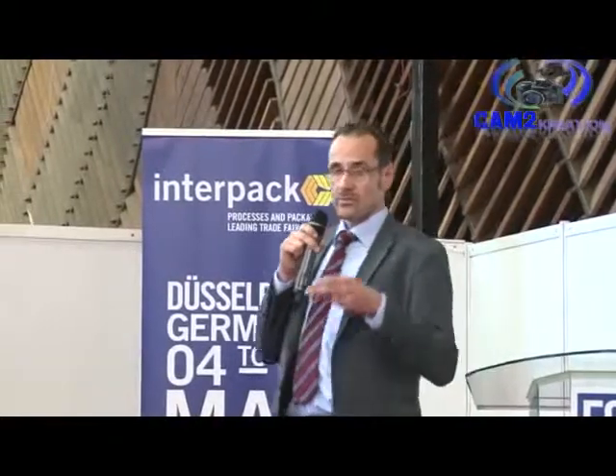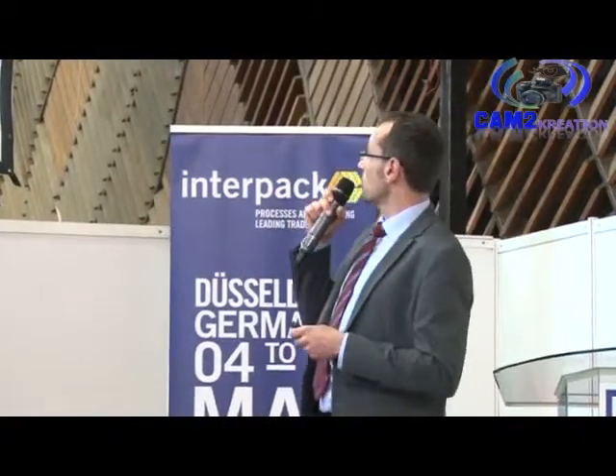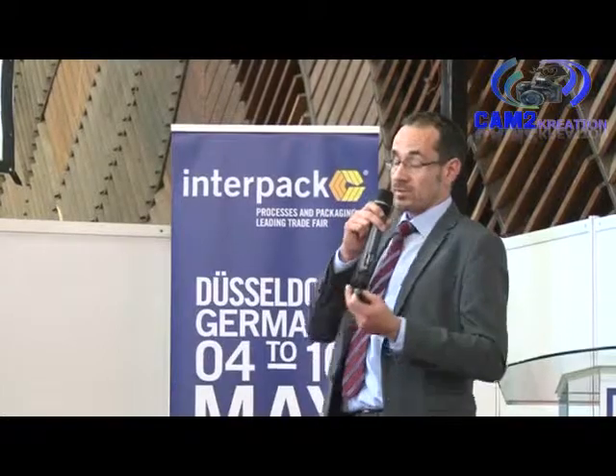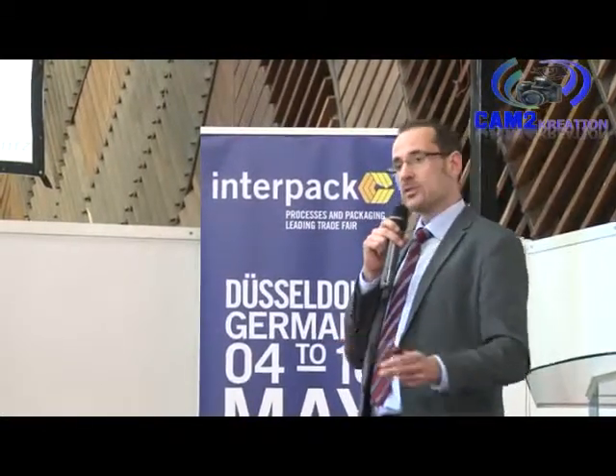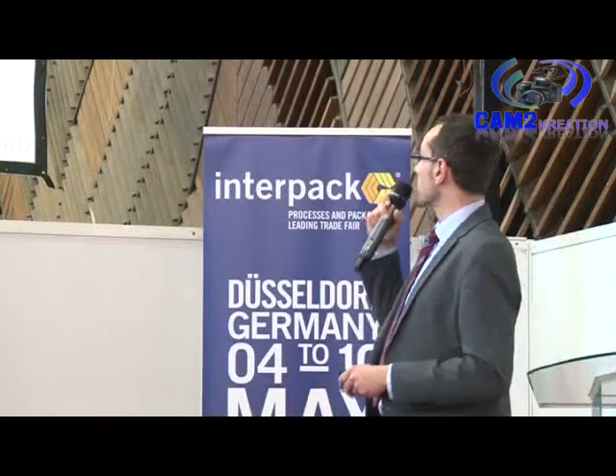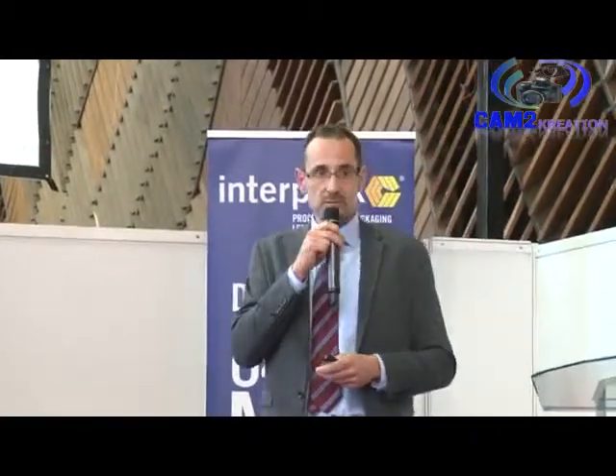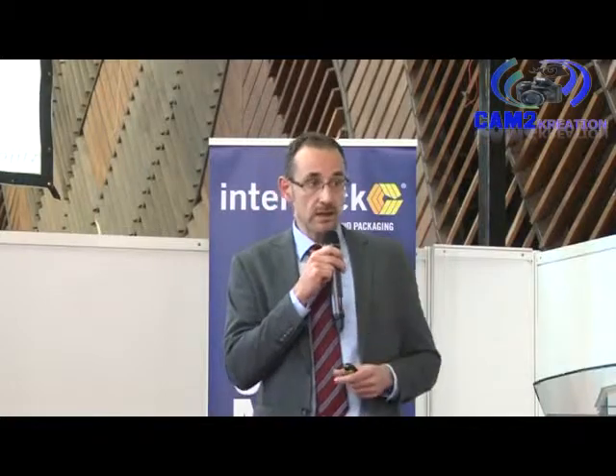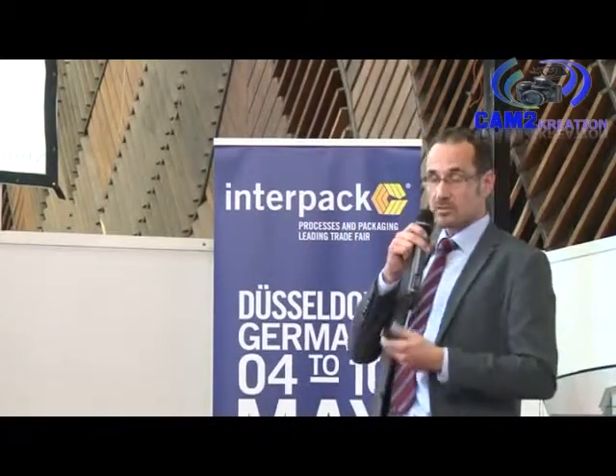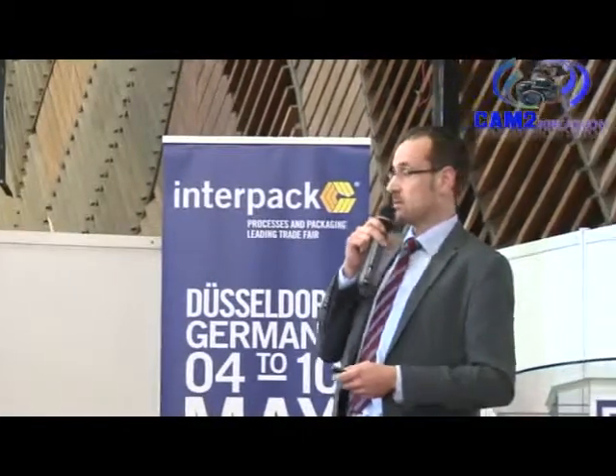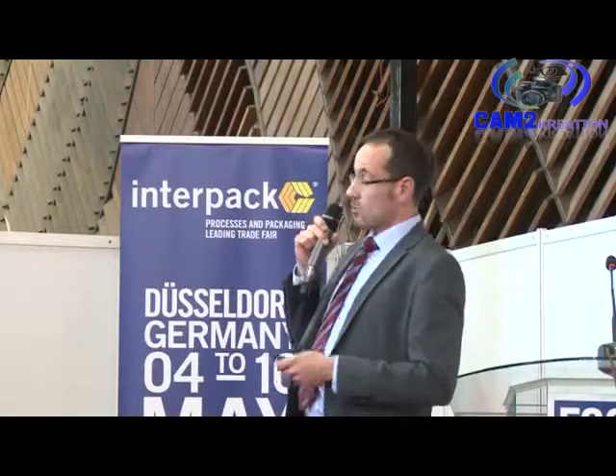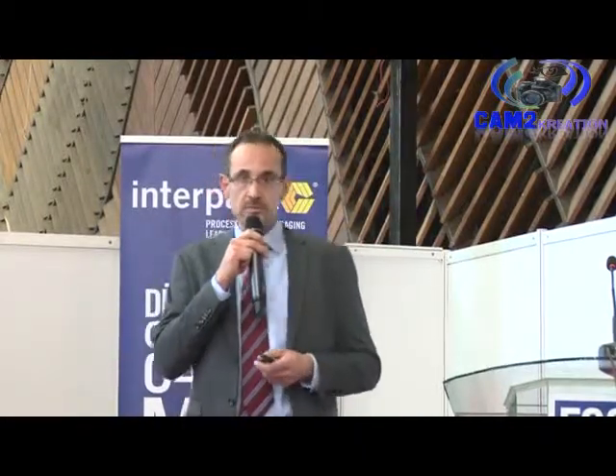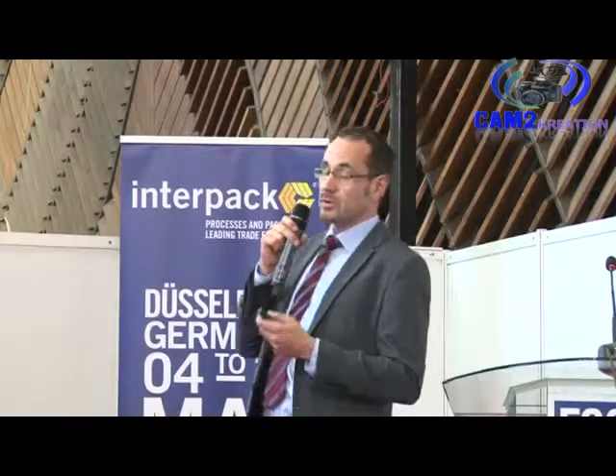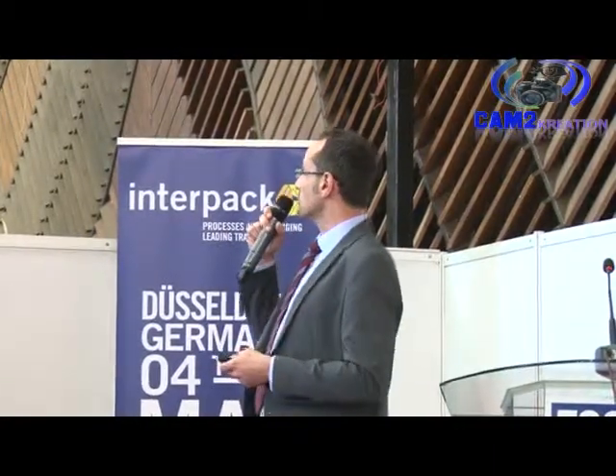The advantage of putting in nylon is to increase the storage and shelf life, because you suck out the oxygen, you will have more or less no oxygen in the package, and the medium gas barrier also avoids, at least for some time, ingress of oxygen. It will reduce waste because you can down-gauge films, as in the example I just gave you, going from a very thick PE film to a much down-gauged film with nylon. It means you will reduce the plastic waste, which I think is also a good topic in Africa, in Kenya. Also, nylon gives you a very good aroma barrier. It gives you a decent gas barrier, which will reduce the dehydration of the foodstuff and also the weight loss.